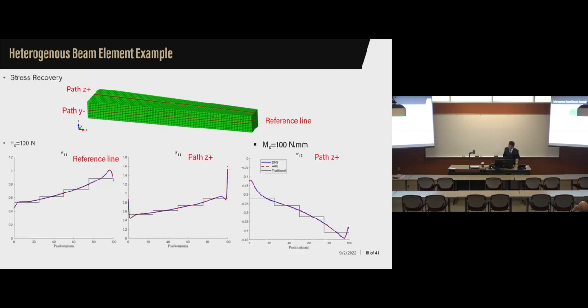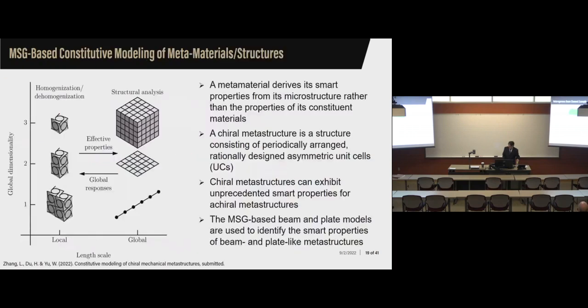But if you look at the stress distributions, you'll find out their difference. The traditional way, actually, you have piecewise constant distribution because when you do that homogenization, you basically made the assumption that this beam is made of piecewise constant cross-sections. And when you reduce that into a 1D model with a series of cross-sections, that's how wind turbine analysis is done. They cut into, you know, hundreds of stations along the span. And then the stress will be a zigzag constant distribution through the segments. But using the new heterogeneous element, you'll find out we have almost perfect agreement with the DNS.